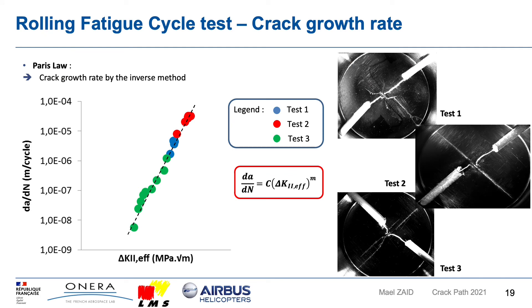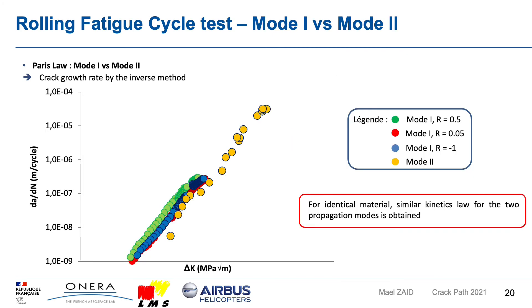The initial objective was to establish a crack growth law for a crack loaded in cyclic shear mode with a superimposed static biaxial compression, taking into account complex physical phenomena between the crack lips. Estimating the Paris law according to the amplitude of the effective stress intensity factor, we managed to find a single kinetic law for all tests, compared to the previous estimation with nominal stress intensity factors. A comparison between propagation kinetics in mode 1 for different loading R ratios and the kinetic law in mode 2 shows that for the same material, similar crack growth rates can be found for the two propagation modes.